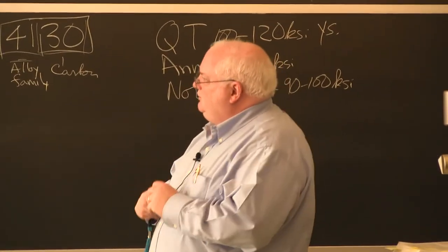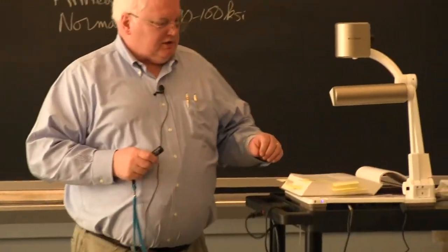and you get this characteristic C-curve behavior. And this temperature of transformation is the beginning of the transformation from face-centered cubic to body-centered cubic. There's the 50% point, and here's the end point, 100% transformation to body-centered cubic. This curve is called a sigmoidal curve, okay? If you're a metallurgist, you can study this for a whole semester, just that one curve, and nucleation and growth kinetics. Ooh, how exciting. I had to do it once.